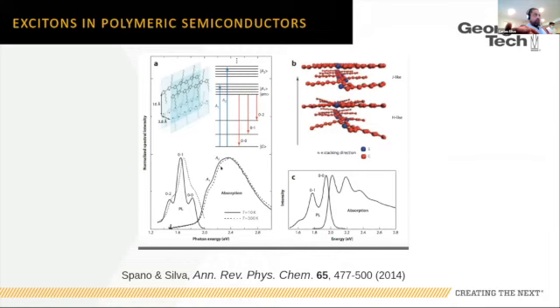But we can do some processing tricks, and Natalie Stingelin, there are very well-defined ways to do this, where we can turn the same material into a J aggregate. This is not the same batch, but we can do that. For an H aggregate, the signature is a suppressed 0-0 with respect to 0-1. A J aggregate would have an enhanced 0-0 to 0-1. And I should say H-like and J-like really to describe that we're in one limit or the other.